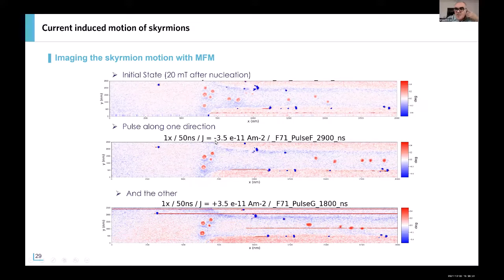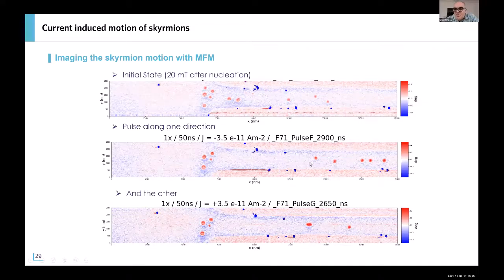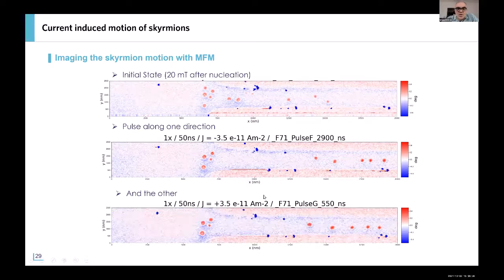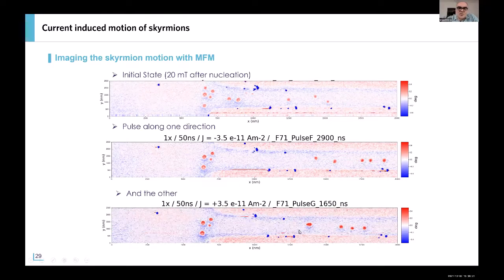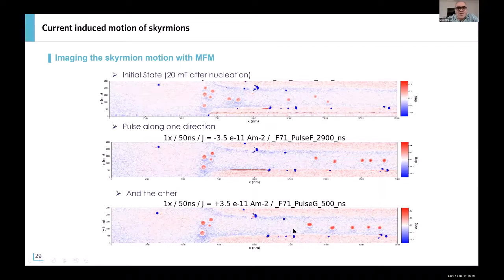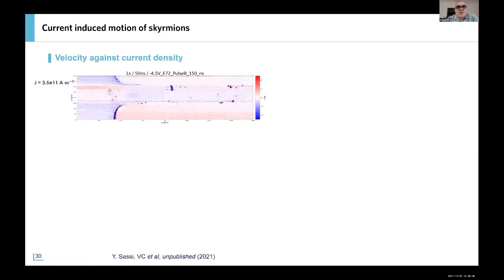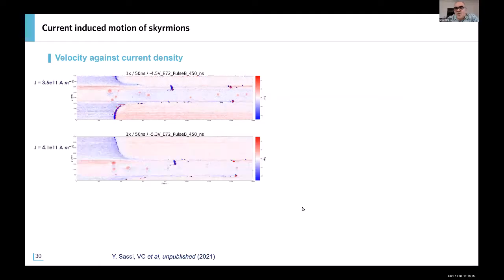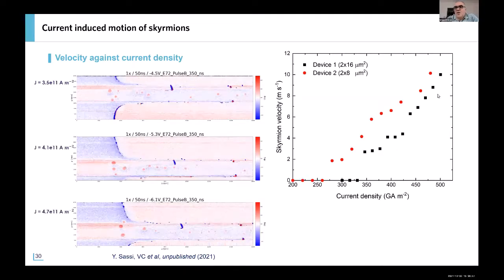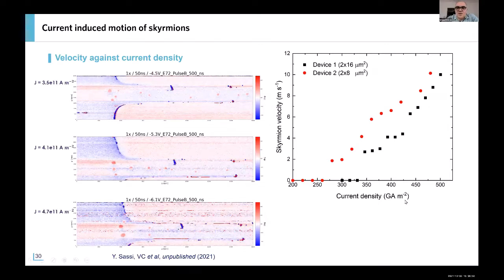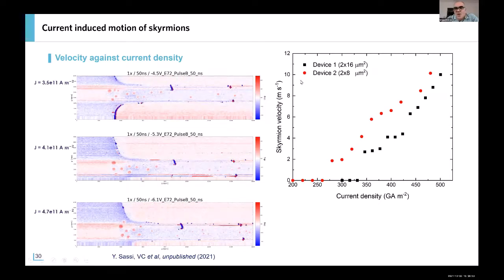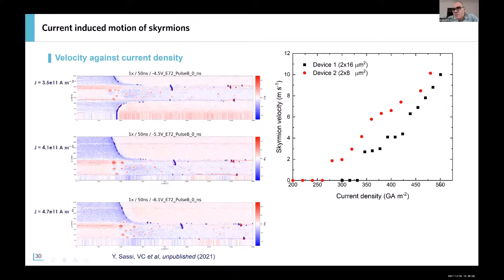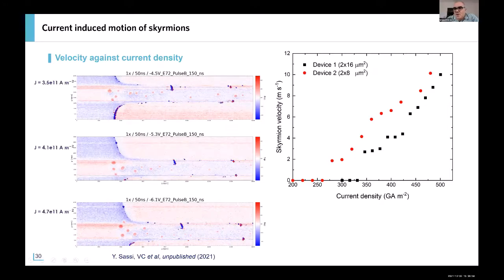So for one sign of the current that is injected, you move the skyrmions to the right, and when you change the sign of the current, you move the skyrmions to the left. Then you can see what happens when you increase the intensity of the current that is injected, and these are different movies, and you see that there is an increase of the velocity as a function of the current density. For this particular case, we reach, because we limit the maximum current injected, about 5, 10 to the 11 amps per meter squared.